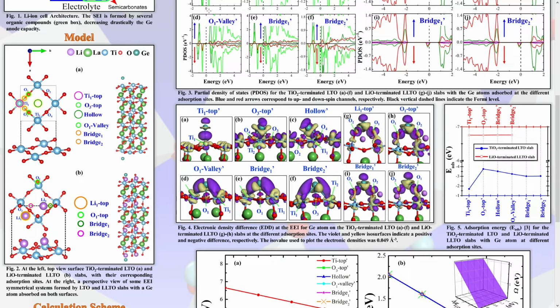For the oxygen top and hollow cases, the germanium sought to interact with two oxygen and one titanium. For the other cases, the germanium seeks to interact with two titanium atoms and one oxygen. In all cases, since there is an accumulation of a positive electronic difference between the surface and adsorbed germanium atom, the formation of germanium-titanium and germanium-oxygen covalent bonds can be observed, in agreement with the results obtained in the partial density of the electronic states.